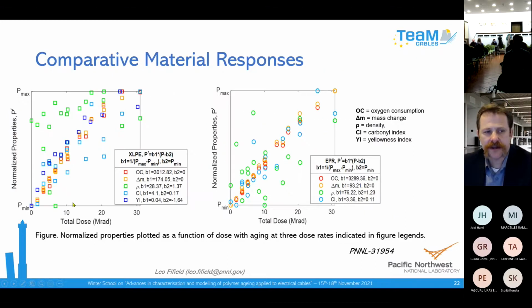So this, just in summary, shows normalized properties: oxygen consumption, mass change, density, carbonyl index, and yellowness index for XLPE and EPR with exposure to different dose rates of gamma radiation. This is versus total dose. Some of the properties like oxygen consumption and mass change were very linear from the beginning. So they proved to be good candidates for sensitive measures of aging, whereas the green dots, green squares here are more all over the map for density. So density didn't end up being, in this experiment, as good a measure as the others.